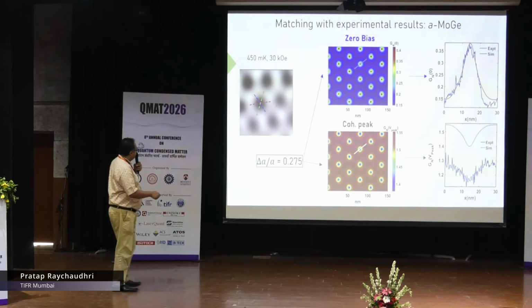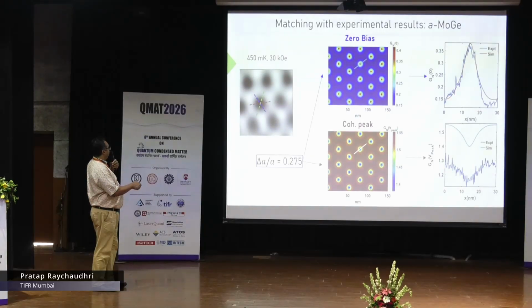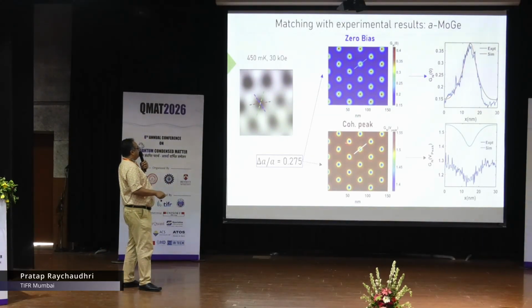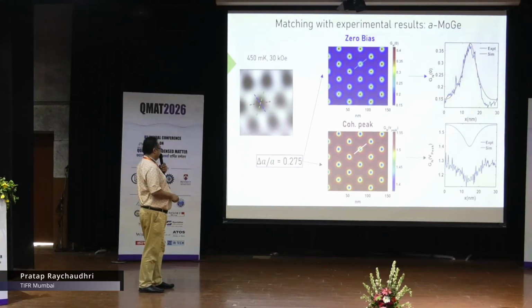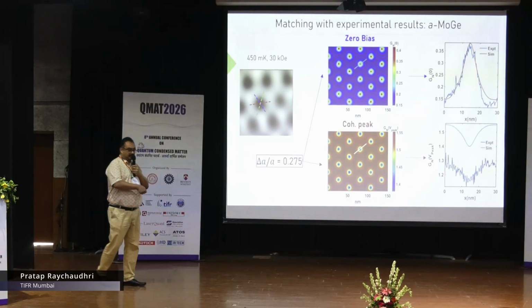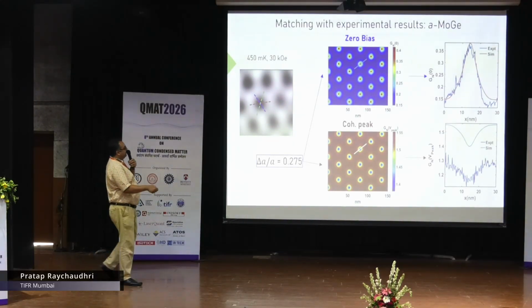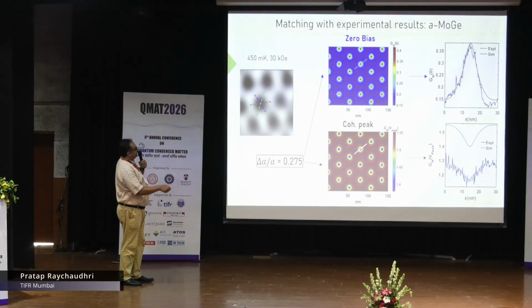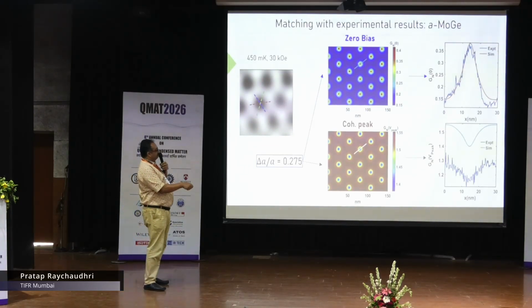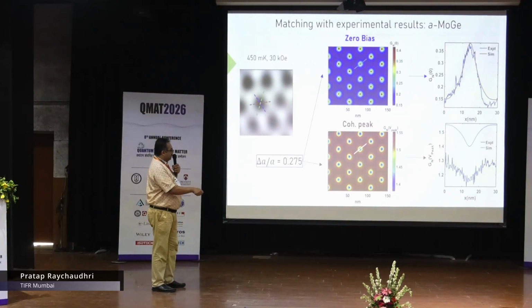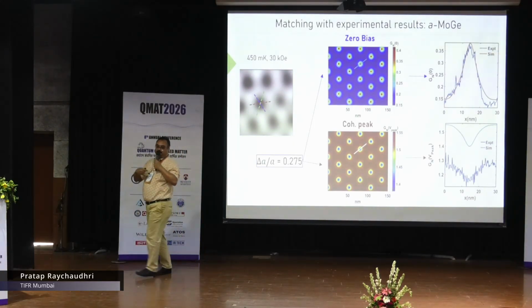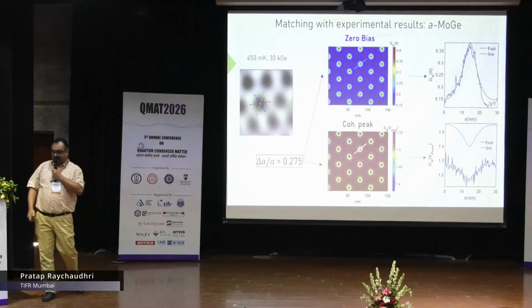Okay, so now I can take experimental data, this is at 450 millikelvin, 30 kilo-Oersted. I simulate this conductance map at zero bias and coherence peak with a given value of relative fluctuation delta A by A. And then I compare this variation of zero bias conductance along this line, theory and experiment. You see that they match extremely well. The red line is what I have simulated, and the blue line is the data. At the coherence peak, there is a slight discrepancy. The amplitude of the variation matches very well. The absolute value has a difference, and this is primarily because we are ignoring circulating current effects.